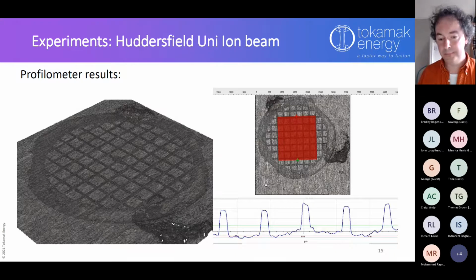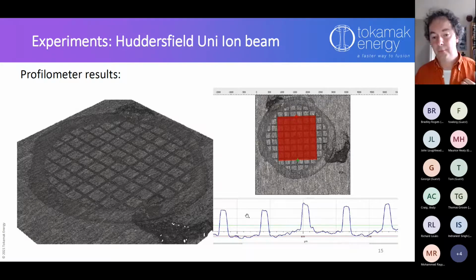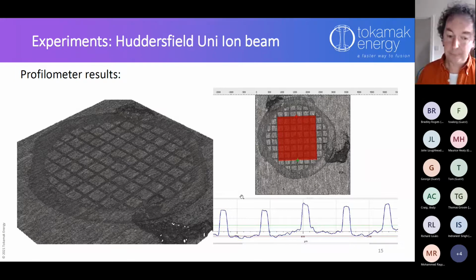And when we do a profile with an optical confocal profilometer, what you get is these peaks. So this is the bit that was protected underneath, sort of where I'm wiggling the mouse around now. That would have had a bit of molybdenum wire from the grid over the top of it. This section here has been eroded away, and we can measure this drop to measure what the erosion depth has been. Once we've done that, we can calculate from that depth what the sputter yield is. We can also do the same by a mass measurement. So we've got 2 methods, and we use this to work out what the sputter yield is of these samples.